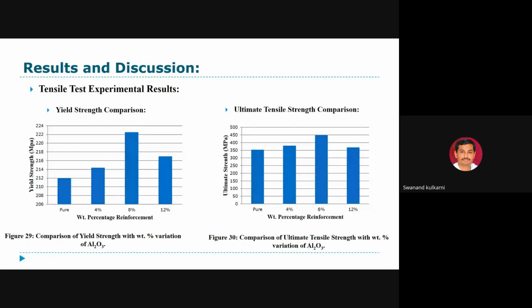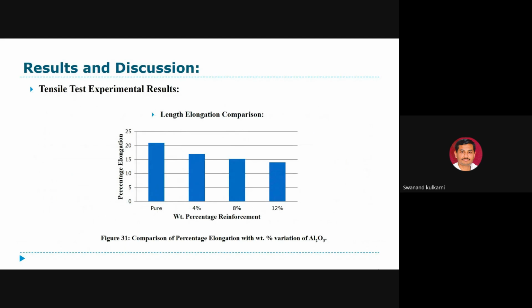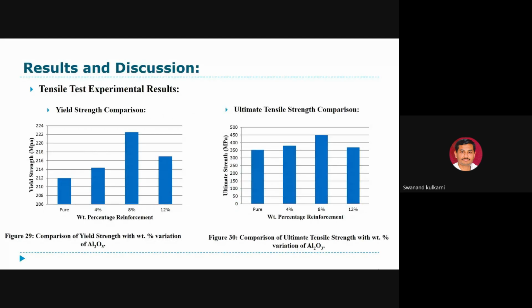So for validation, we have three kinds of validation. Either we can go for the experimental analysis, we can go for the modeling technique, or we can go for the microstructural studies. As far as the present investigation is concerned, as the reinforcement percent increases, the yield strength increased up to 8%, but later on the yield strength did not improve, and that may be because proper wettability was not observed. But up to 8%, the alumina added inside the aluminum matrix composite successfully increased the yield strength up to the expected level.